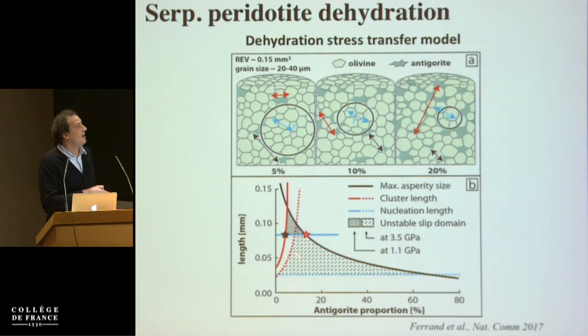So basically, you have 3 lengths here. You have the cluster length of the serpentine. Here you have the size of the olivine asperity, and here this would be the nucleation length. And in this little window where you have enough antigorite, but just enough, but not too much, so that the olivine asperity will be large enough and larger than the nucleation length, you will produce acoustic emission.